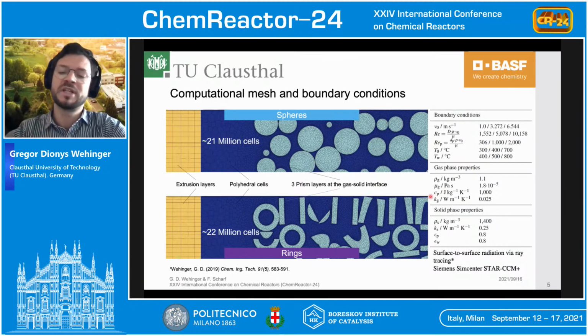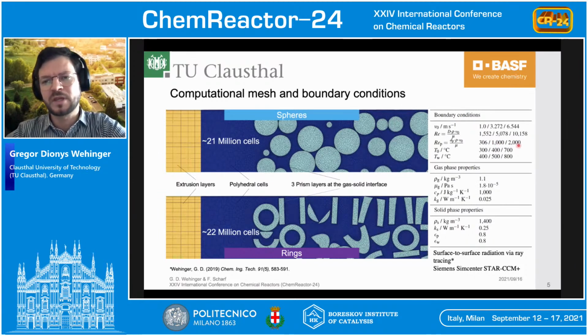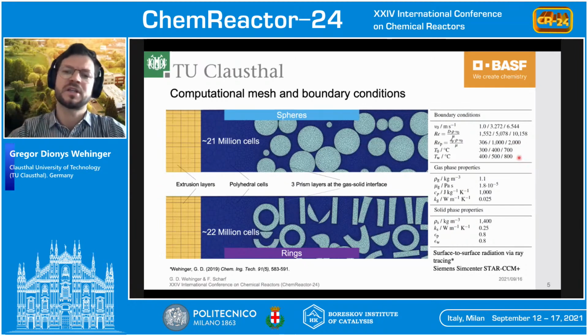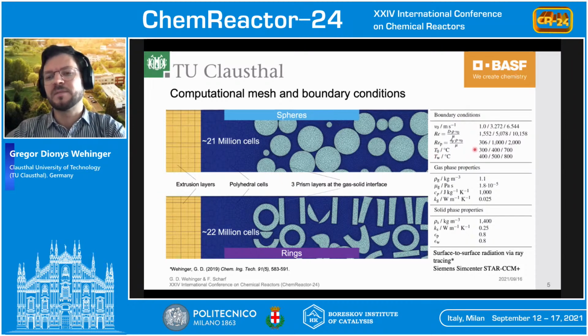So on the right-hand side, I just got a quick summary of the boundary conditions. As I said, we investigated 3 different particle Reynolds numbers, as you can see here. 306, this one corresponds to a 1 meter per second superficial velocity. Then we also looked into a little bit higher velocities, resulting in particle Reynolds number 1,000, so turbulent regime, and 2,000. On the other hand, we looked at 3 different temperature ranges, namely the temperature range is always a constant between the inlet T0 and wall TW. And we investigated 300, 400 centigrades, 400, 500, so milder conditions, and then 700, 800 centigrades, which are typically found, for example, in steam or dry reforming conditions.